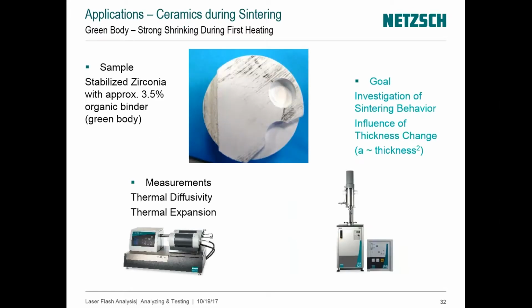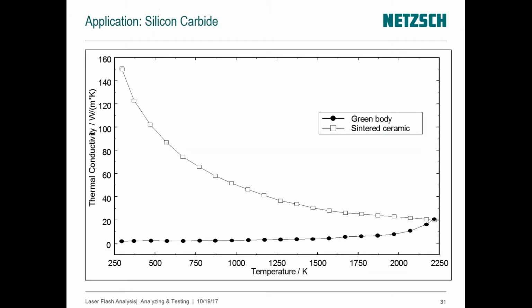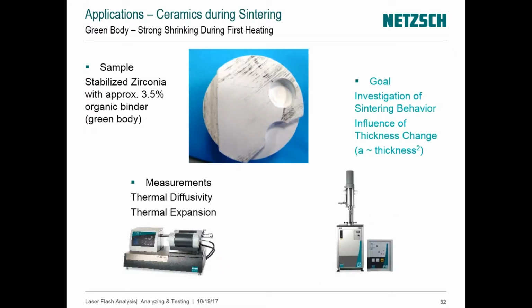again for ceramics. The one thing we want to show here is that very often in that particular case, I did not account, or we did not show, the influence of sintering while increasing the temperature. And here what we'll be doing in that case, we will account for that, because the specimen is shrinking as expected, as desired, and as a result, the thickness of that specimen will change. It's very important to do that too. So we'll bring to bear also other instruments or other techniques.